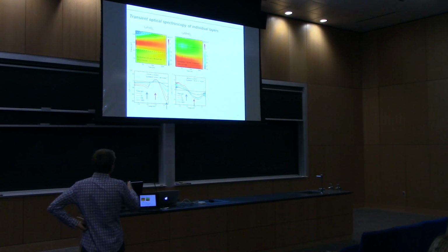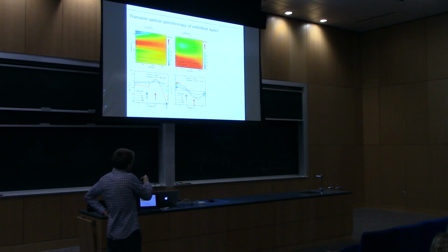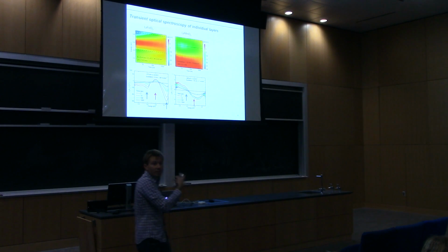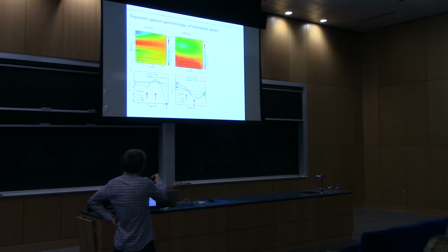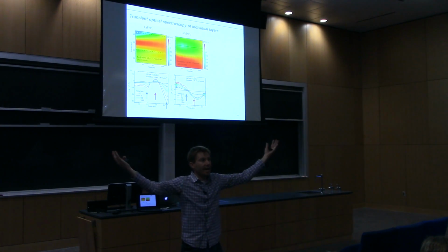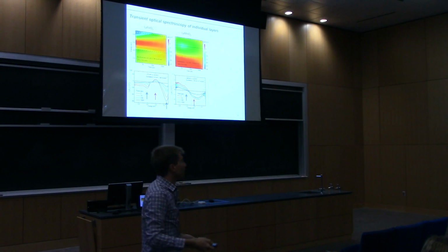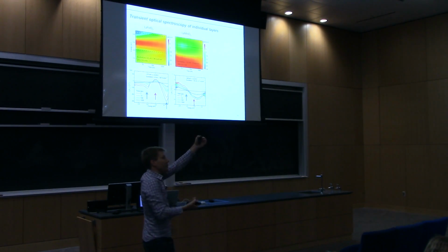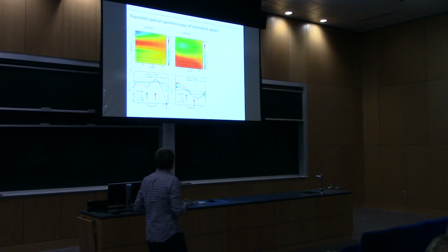Here's the lanthanum manganite. There was that transition at 3 eV. Again, we get a negative transient around 3 eV. This is the same energy at which we get the positive transient in LFO, so that's going to be important. And down here at lower energies, 2.5 eV, we see a positive transient. So that's what the two materials look like when they're not attached to each other. Let's attach them together in a 20 nanometer bilayer, and see what we get.